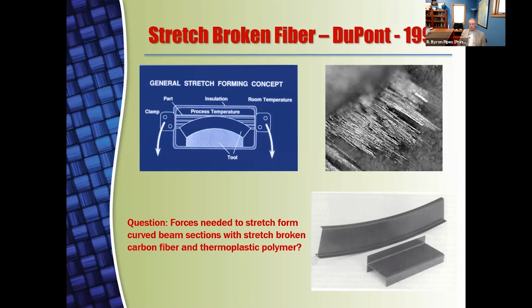Well, the machine works on carbon fiber, so we've stretch broken carbon fiber, we've impregnated it, and lo and behold, you can indeed form it. You can see at the lower right a straight channel which has been stretch formed into a curved one. So it did work. The question to me that they were asking: can we predict the forces necessary to carry out this stretch broken forming or stretch forming? And I had to think about this for a while. It was not a subject I had worked in before, but clearly they were talking about a stretch broken carbon yarn in the presence of a liquid polymer because they were at the melt temperature. And so the question then was, could you anticipate what that property would be?